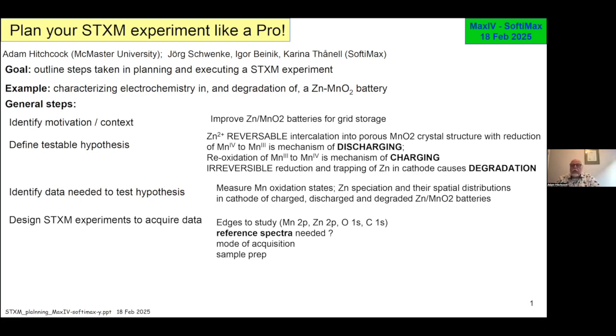Scour the literature before you enter into a STXM project so you don't reinvent the wheel. You may have to check the actual energy scales. Often the data in the literature may be correct, but incorrect as to energy scales. So it's something to be conscious of. There are a number of ways of acquiring some data. You can do electron yield, you can do fluorescent yield techniques, which sense different parts of the material, the surface or the bulk. But the transmission technique is actually well suited to what we're trying to do here.